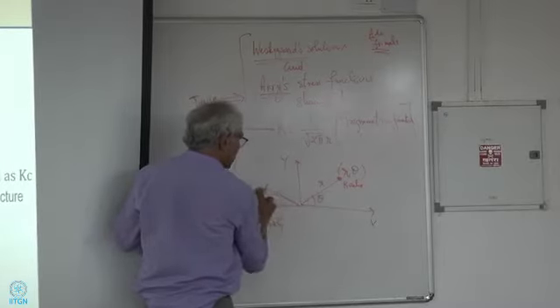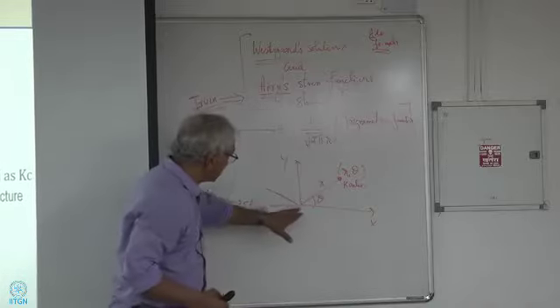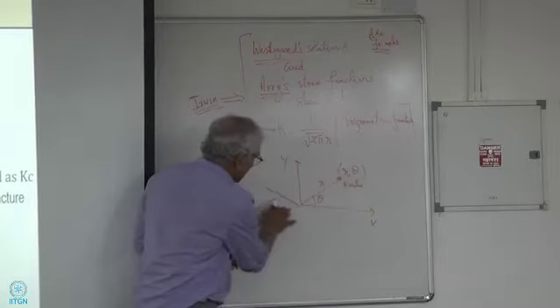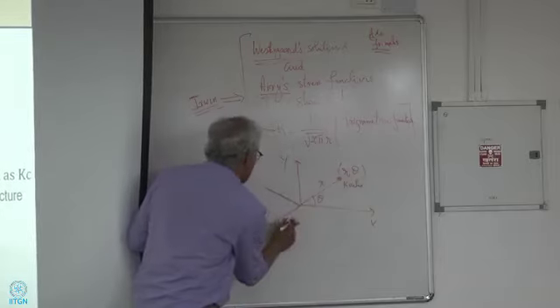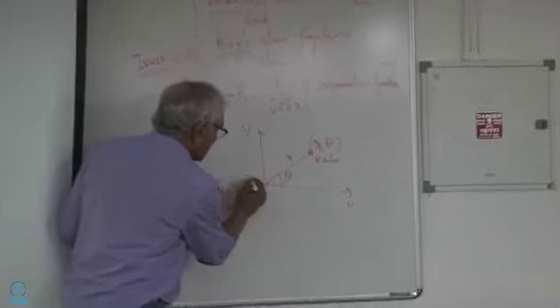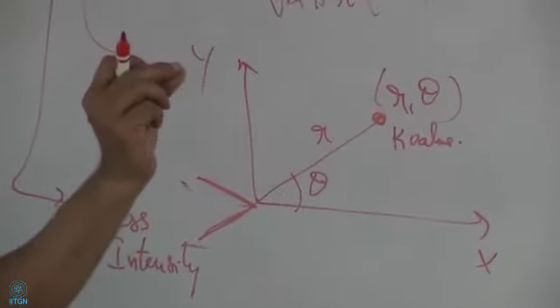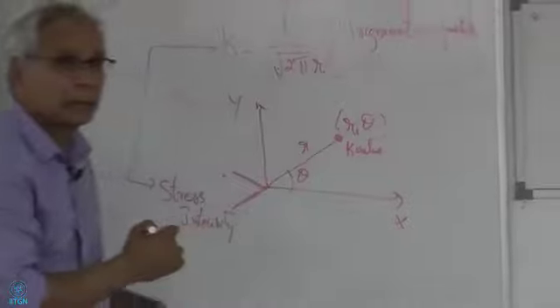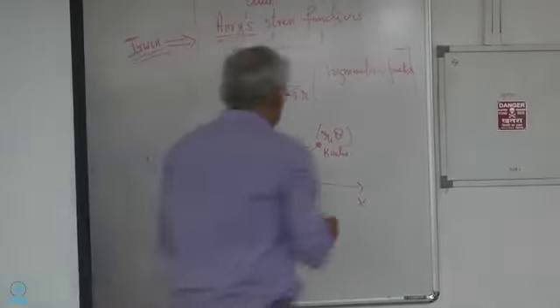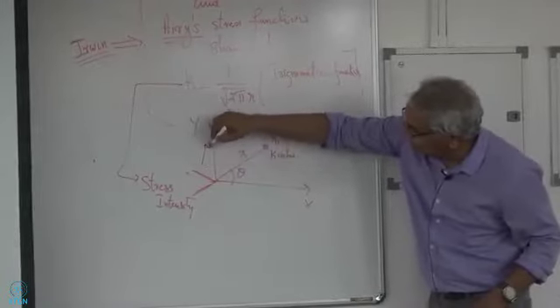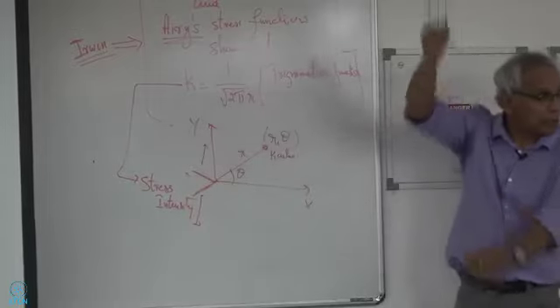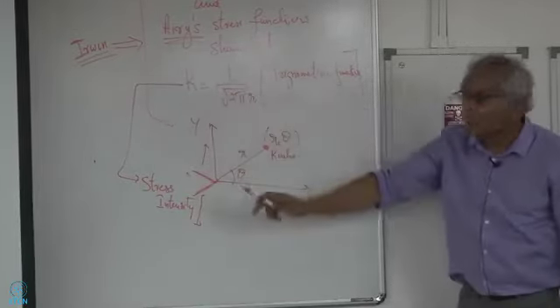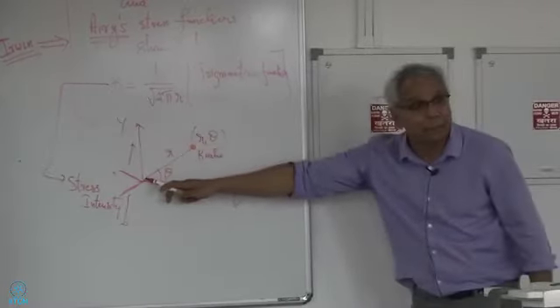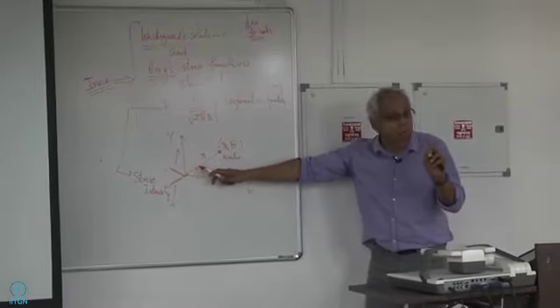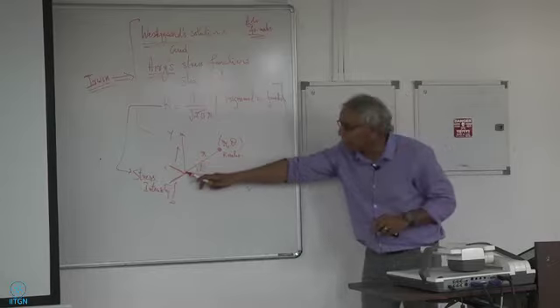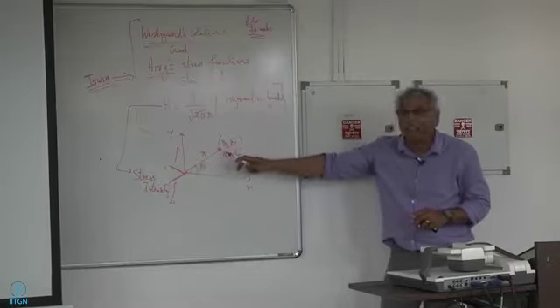If you want to put this crack there, that is fine. So what I have a situation here is a very sharp crack, not a notch, but very sharp. Actually, there's a very sharp crack here. I got a coordinate system in front of it. And I'm loading this crack in a tensile mode or a mode 1. I'm opening this crack. On the distance away from this crack tip, a very sharp crack tip, atomically sharp crack tip, that's the key. Atomically sharp crack tip, I can define a K value, a stress intensity value.